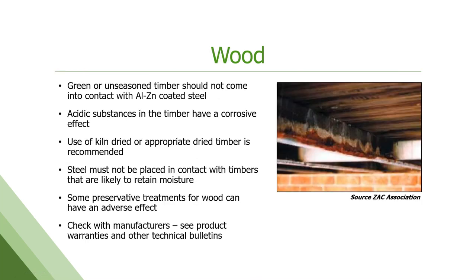Wood. Obviously, there's almost always going to be some kind of wood used on almost any kind of construction. Green or unseasoned timber is bad because of the acids in it and the water that it holds causes corrosion. So kiln-dried timber is best. Don't want to place it in direct contact with timbers that are likely to retain moisture. Again, it'll start to corrode it. There are some treatments, especially fire retardant treatments that are copper-based, that can leach out and be problematic as well. So it's always good to ask what the treatments are. And we have a list. It's actually spelled out in the warranties for this product, what treatments can and can't be used with it.